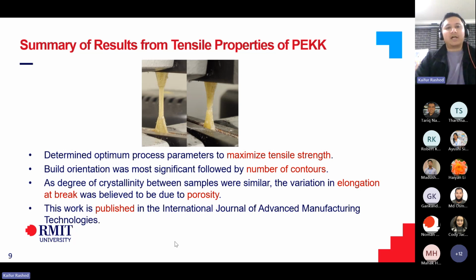So, as a summary of results from the tensile stress properties, I determined the optimum process parameters to maximize tensile strength. And I found that build orientation was the most significant parameter that affected the tensile properties, followed by number of contours. Numbers of contours were also important in determining the tensile properties. And as I said, the degree of crystallinity was similar, so variation in elongation at break was believed to be due to porosity. And I've published this work as well in the International Journal of Advanced Manufacturing Technology. So if you want more details, please do check it out.